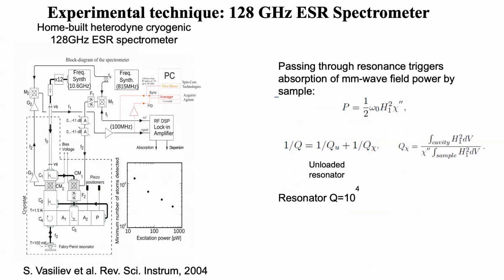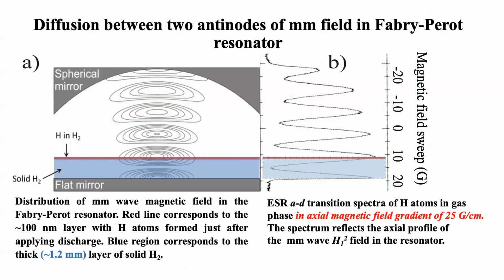We study our samples. What was our idea? Our Fabry-Perot cavity has the following distribution of magnetic field. We have a mode, TM005, so this is the antinode of millimeter waves. What it means is, if you fill this sample cell with hydrogen gas, spin polarized hydrogen gas at this temperature, and apply a gradient magnetic field so that you can see the resonance for each of these antinodes, you will see a maximum of the signal for the gaseous hydrogen.